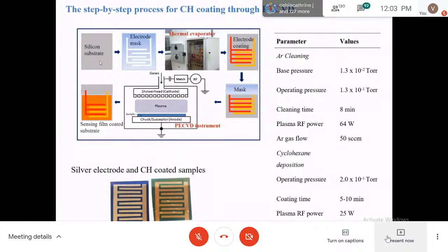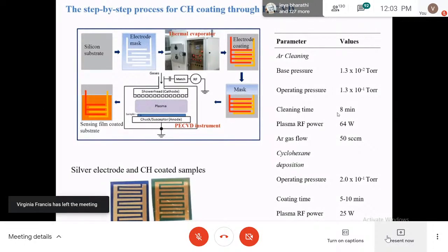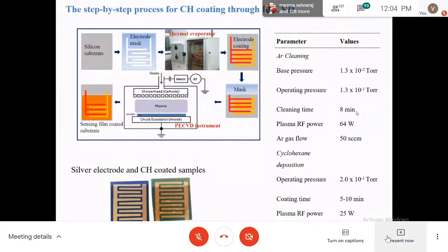So what happened? We take the silicon substrate, and we have to use a mask to deposit this silver electrode. Then we load it on the thermal evaporator and coat the silver electrode here. The parameters used for the silver coating are given on the right side. First we have to clean the silicon substrate, and then we coat the silver electrode.